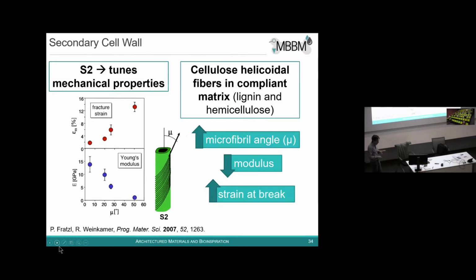Now, we know that the S2 layer, the one which is the thickest, which occupies 80% of the thickness, is composed of cellulose microfibrils, which are spirally wound around the wood cell wall. So this is a single wood cell, which is an elongated cylindrical structure. And this is cellulose, a stiff crystalline polymer composed of sugar-like molecules, which form characteristic angles. And we can measure these angles with X-ray diffraction. And what we know is that this angle is used, by nature, to tune locally the mechanical properties of the wood material without changing chemical composition.